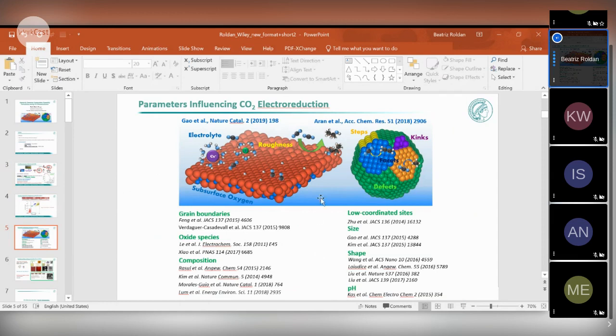and it has been shown that the pH of the electrolyte will also affect the selectivity. Even more, when you go to the nanoscale, you have nanoparticles, and you need to consider that as a function of the particle size, you have specific sites at the surface, steps and kinks, that are also going to affect the adsorbate binding and also the binding of intermediates. If you play with the particle size and shape, you're going to affect all of this. So this is very complex.